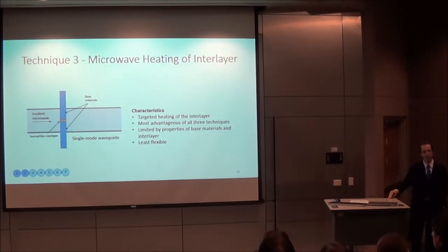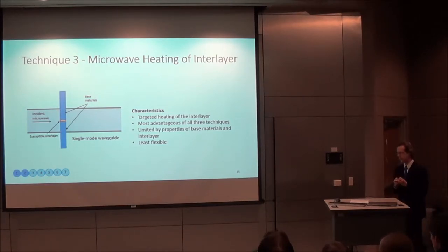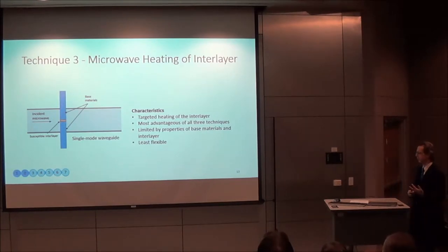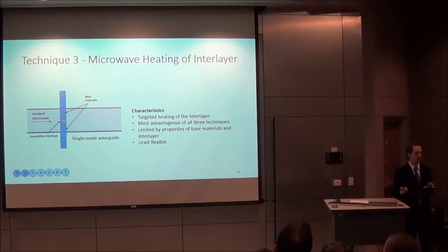Technique three is where there is an interlayer between the base materials that is selectively heated. In this method, the heating is targeted right at the interlayer. It's the most advantageous of all these three techniques, but it is the most limited in terms of the base materials and the interlayer itself. It has to be susceptible to microwave heating. And there are the most limitations in terms of joint size and shape configuration with this method.